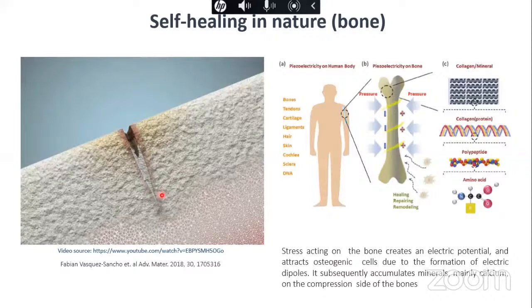If there is a fracture in the bone, since bone has a lot of collagen in it, it's like a composite. Collagen has polypeptide chains composed of amino acids, which are chiral, so you have a polar arrangement in the crystals. Because of that, bone is actually piezoelectric. Any piezoelectric material under stress develops opposite charges. For example, as you can see in this picture, when you put bone under stress, the charge separates and one side becomes positive and the other side becomes negative.